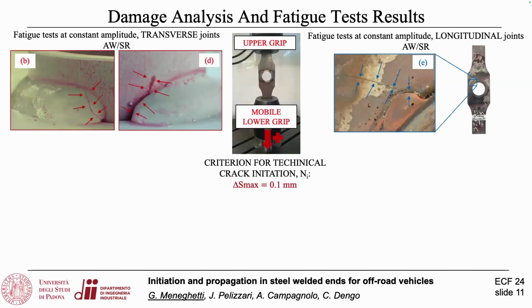So with this failure criterion, the crack is indeed not very short. It is some 10 or 20 millimeters long. And you see multiple crack initiation points. Going to the longitudinal joints, you see that the crack initiation point was always at the weld toe at the plate side. This is the plate, this is the tube. The applied load is vertical, and you see here the crack initiation point, and then you have the crack propagation in the main plate.